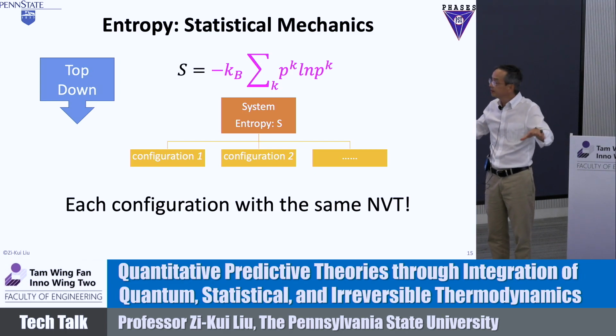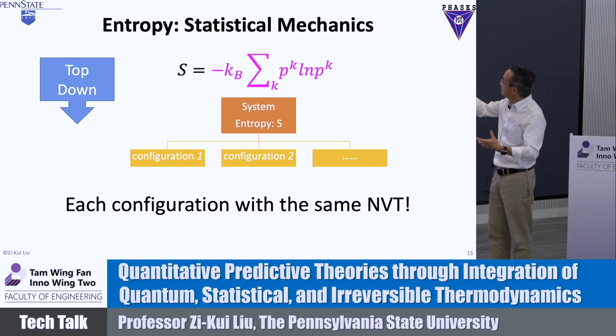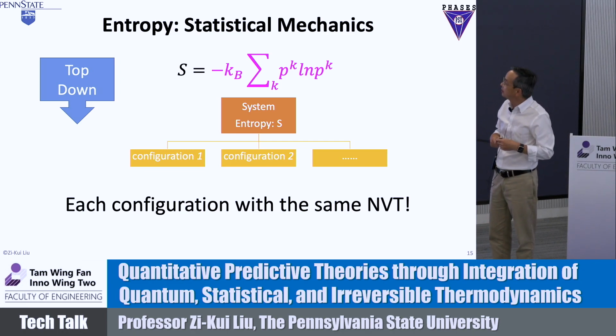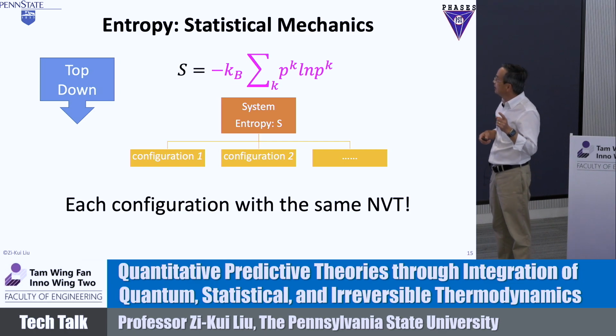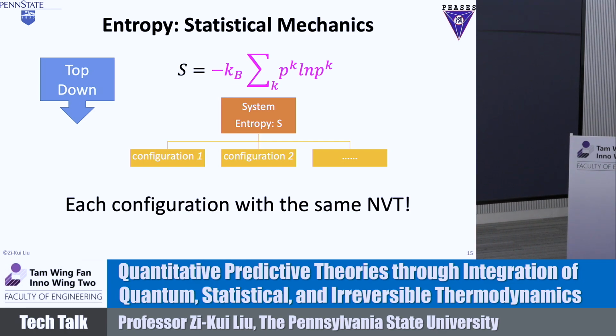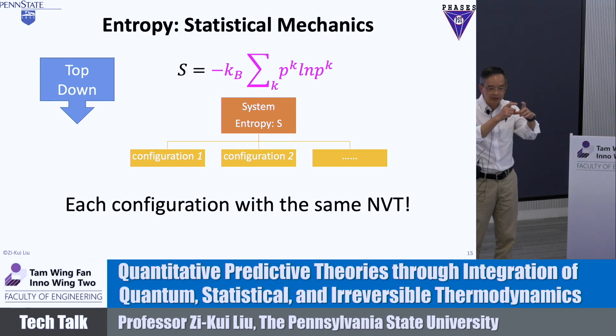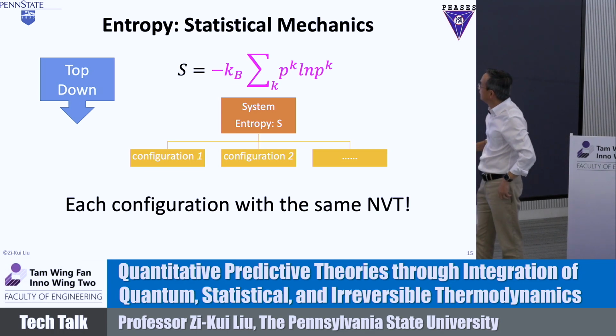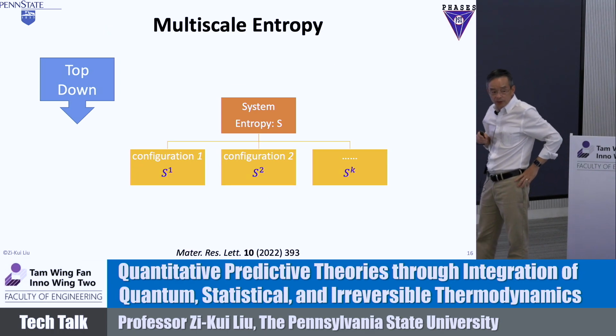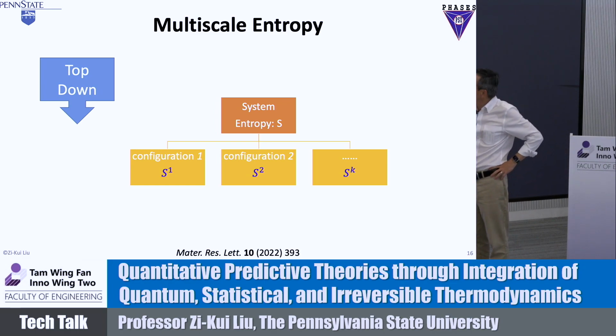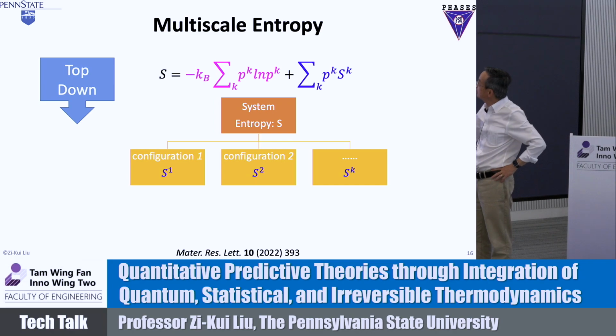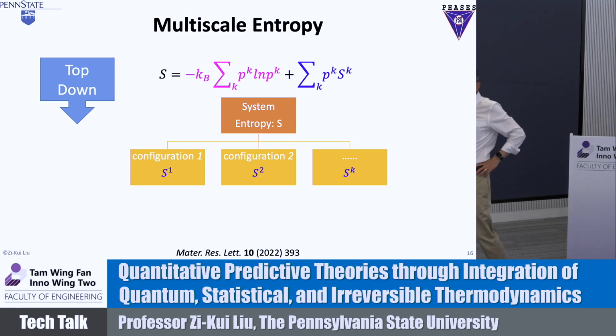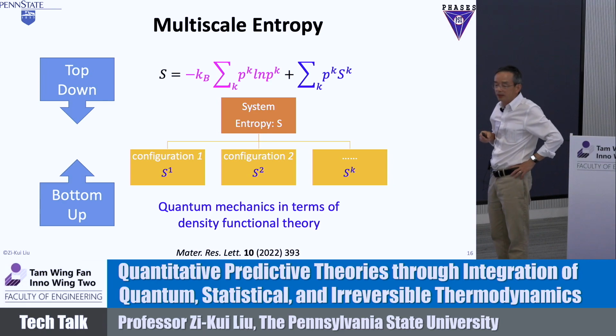You have configurations. You compute the entropy of the system, which is the summation of pk log pk times k. Very important in Gibbs's work is that each configuration must have the same NVT as the system. You cannot take a part of it; you have to take the whole system. However, if each configuration has its own entropy, you have to add it. So in addition to the configuration entropy among configurations, you have to have the entropy of each configuration together. If you do that, you can go all the way down to quantum mechanics.